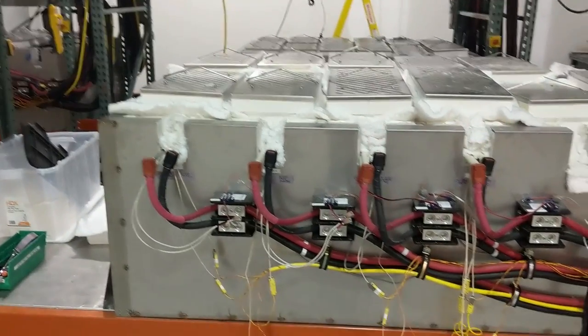When we're talking about liquid metal, they have to run at an elevated temperature. The first battery we worked on — I mean I, with my students and postdocs at MIT — was magnesium opposite antimony. These metals melt around 630–650 degrees Celsius, so we had to go up to about 700 degrees Celsius.